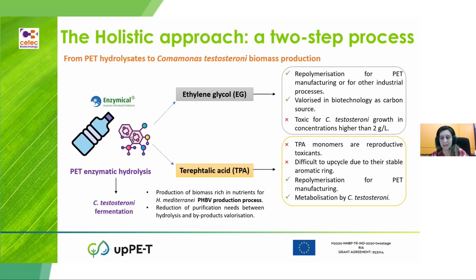And if it can be correctly purified, they can also be repolymerized for PET manufacturing. And we can also metabolize this monomer by Comamonas testosteroni. And this is what we have developed in the upPET project. So from the whole mix of the enzymatic hydrolysis of PET, we feed with all these mixes containing ethylene glycol and terephthalic acid without any purification. We use this mix to feed Comamonas testosteroni and for the production of a biomass rich in nutrients for the Haloferax mediterranei PHBV production process. So with this approach, we reduce the purification needs of the monomers, and we can give other high value applications for these monomers.